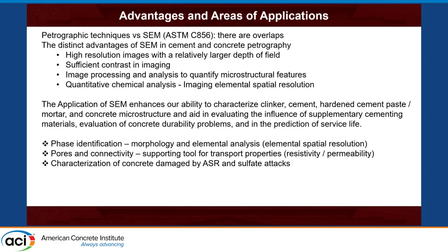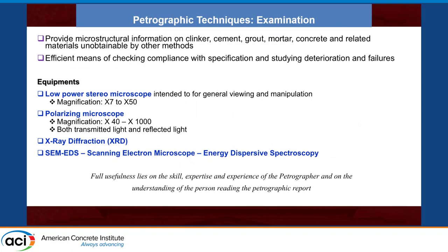The advantages of SEM include high resolution imaging, sufficient contrast, image processing and analysis, quantitative chemical analysis, phase identification, and connectivity assessment. Because we do a lot of nanotechnology and add fine particles to modify the microstructure of concrete, SEM helps understand connectivity for transport properties and links microstructure to measured properties such as resistivity.